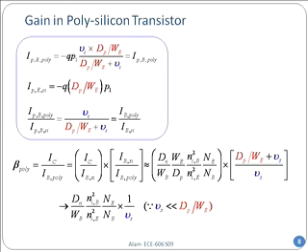So the temperature was not as high as it was supposed to be. The temperature was a little lower. And therefore, instead of having silicon crystal grown in the emitter, they accidentally had polysilicon grown. So they were actually planning to throw it away, right? Because, you know, there's a malfunction in the reactor, so better throw it away.